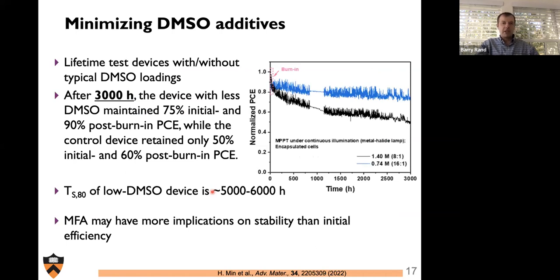So in this device architecture, which is an NIP device architecture consisting of tin oxide and then the FA lead iodide system, and then a spiro layer and then a gold top contact, we see a relatively rapid burn-in over the first tens of hours of the device, followed by a relatively stable phase. And what we see is lower DMSO loading, shown here in blue, has considerably longer lifetime than the device with the remnant DMSO, which we know produces MFA. In fact, if we extrapolate the post-burn-in device with low DMSO, we get an extrapolated T80 of somewhere in the region of 5,000 to 6,000 hours, which is among the higher stability devices in literature.